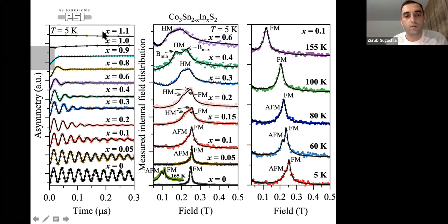In that case, if you follow systematically the field distribution at different doping and temperature, we see that when you go to higher doping, we have this kind of field distribution, which we explained by this incommensurate helimagnetic ordering, similar to MnSi, manganese silicide. And this incommensurate helimagnetic ordering remains also at the highest doping level.